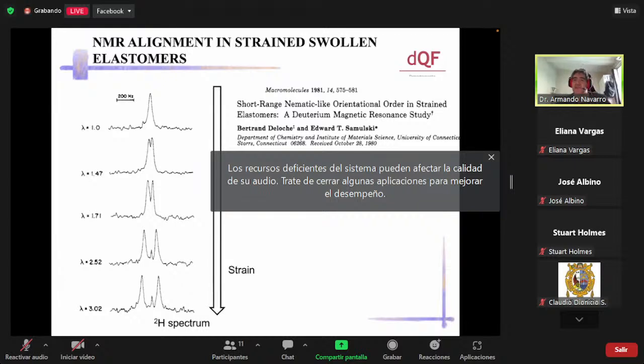Well, in the case of polymer gels, the root of the technique can be traced to this very phenomenal paper, I would say, from Samulski. Samulski is a very well-known polymer chemist with very important contributions. He published in 1981 that if you get a piece of rubber, swell it in a solvent, in this case benzene, if I remember well, and you stretch the rubber, you observe the following. This is the deuterium spectrum of a deuterated benzene. When the rubber is not stretched, you have a stretching factor of 1.0, the rubber is in its natural state.